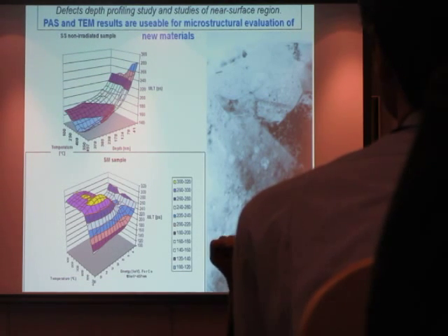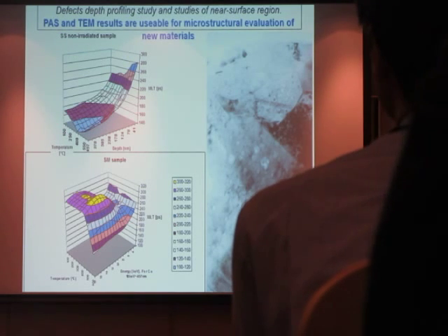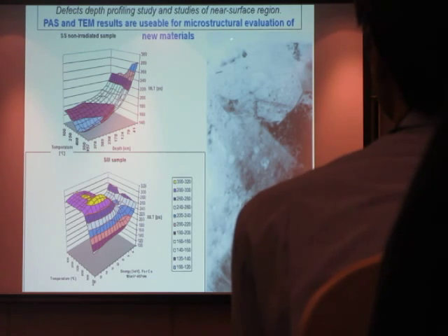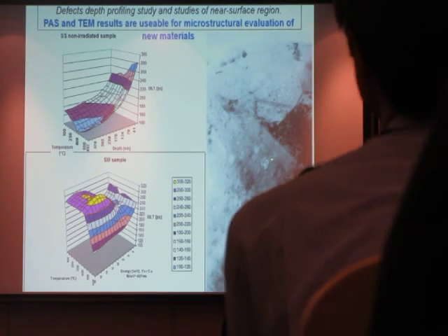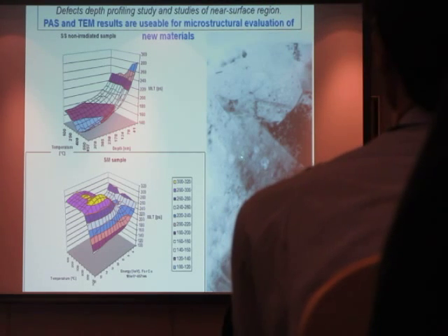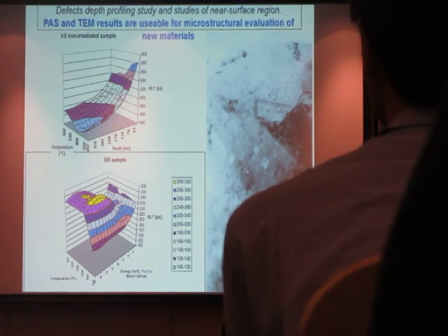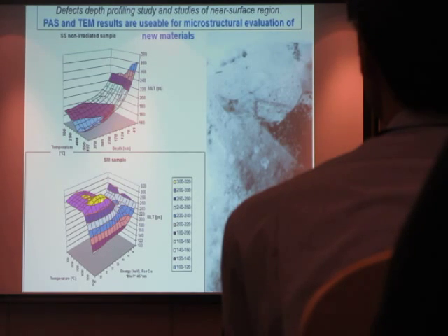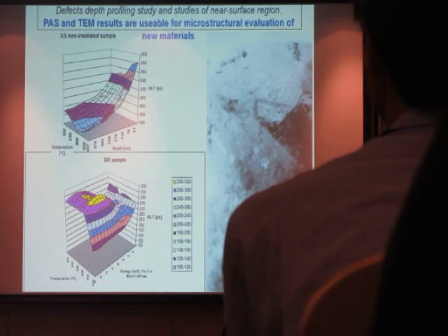A big advantage of positron annihilation is that you can see implantation. Look at the material, it's the surface. You implant hydrogen inside by accelerator. You can recognize by temperature the bubbles of the defects. It's the hydrogen inside, and you can measure it. And you see on the same position the maximum, and by elevating the temperature you can see that these defects are annealed. So in combination there is the picture, and people trust a picture; the graph is the best choice.